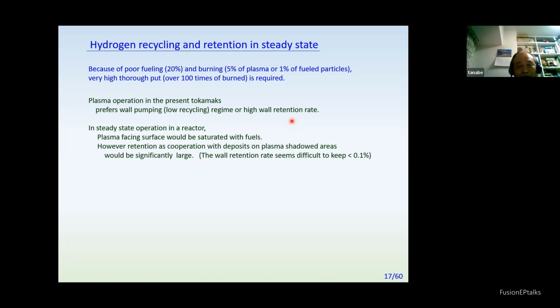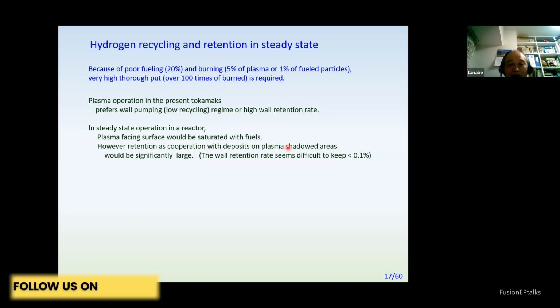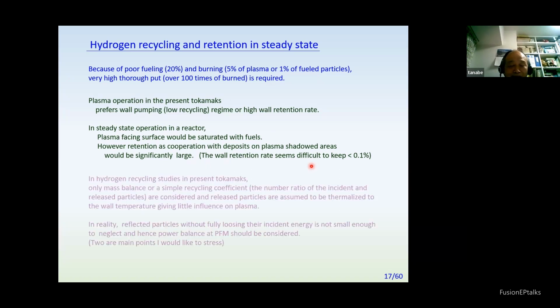But in steady state operation, the plasma-facing surface becomes immediately saturated because the fusion reactor flux to the wall is very high. Most of the wall tritium retention is taken by deposits, because the plasma-facing material is eroded and deposited, and this deposition goes to plasma-shadowed areas, which take up a lot of fuel and continuously increase with time. So keeping wall retention very small is rather difficult.